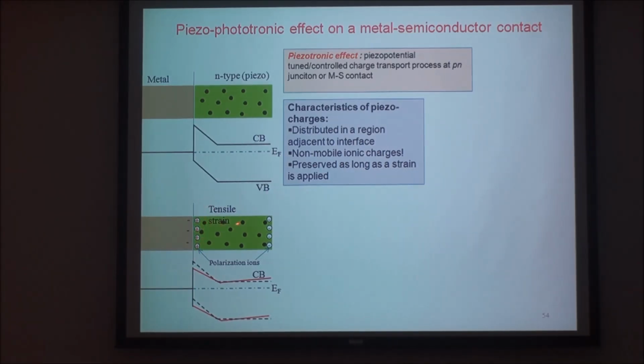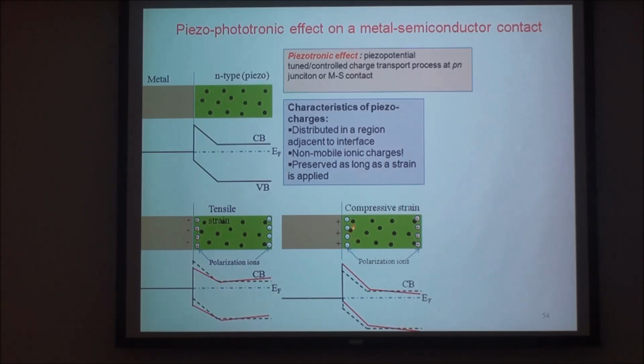If this is the case, even if you have some doping, the doping will not completely cancel this ionic charge, but partially screen it. This is ionic charge. It will not flow, only present at the interface. If you apply strain, it generates charge that is present there. In such a case, it will lower the barrier height for tensile strain. But if you compress the strain, the negative ions raise the barrier height.